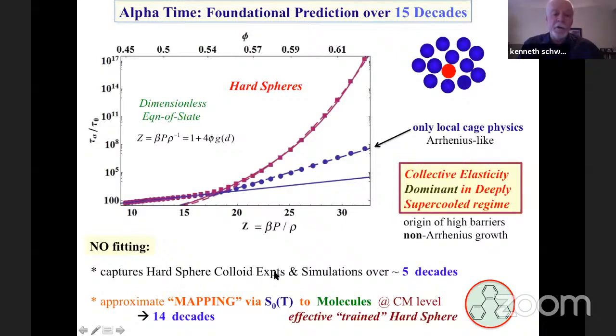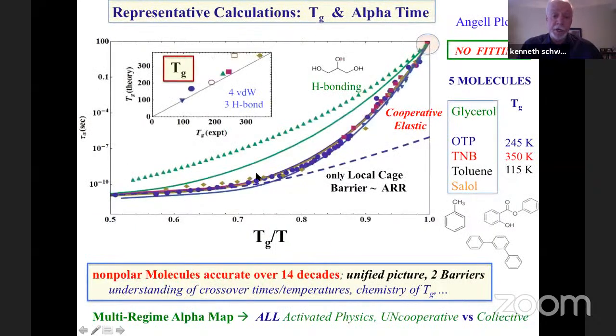We've compared this to hard sphere colloid experiments and simulations, which is a small snippet of this, and there's good agreement. Now, I don't have time to discuss it, but my real interest is thermal liquids and these 14 orders of magnitude. So we've developed mappings where we force the theory, we map a molecule to a hard sphere, but we force the properties of the hard sphere to exactly agree with the experimental dimensionless compressibility of thermal liquids at atmospheric pressure. And when we do that, we can make no adjustable parameter predictions for the alpha time of molecular liquids. And so here's an example.